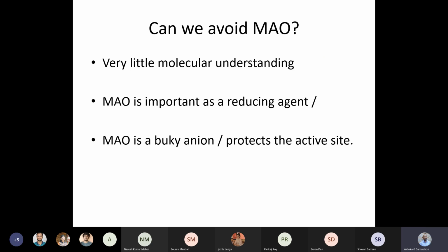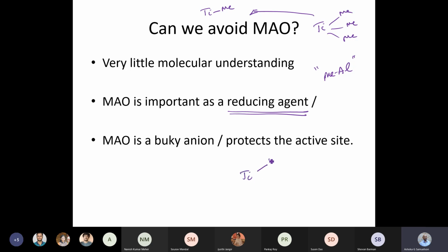As I told you, MAO is important as a reducing agent. It has got this methyl aluminum bond, and methyl aluminum can be reducing, and that is something that we have already seen. It can do transmetallation. So the titanium trichlorides could be converted into titanium trimethyls, and these titanium trimethyls can eliminate ethane and produce titanium methyl groups. And titanium methyl groups can now initiate the polymerization by forming a titanium alkyl, with an insertion reaction first, and then a subsequent coordination site is generated for the olefin,